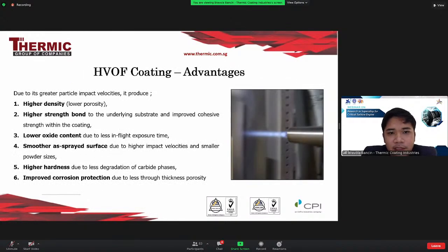So what are the HVOF coating advantages? It's higher density and lower porosity because of the kinetic energy from the impact of the powder on the substrate. We can see this is the flame test before the coating is conducted. We can see here like diamond, because it is very fast.